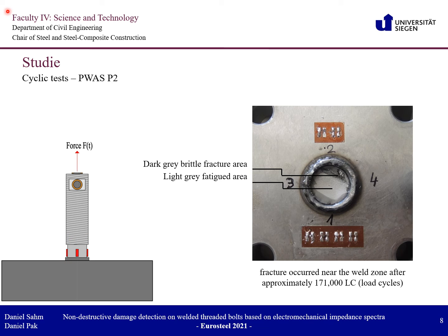The arrangement made it possible to measure the strain change over the circumference of the shank during the tests in order to sense the introduction of the fatigue crack at an early stage. In case of specimen 1, a fracture occurred near the weld zone after 171,000 load cycles. In the picture you can see a light gray fatigue area and a dark gray brittle area.